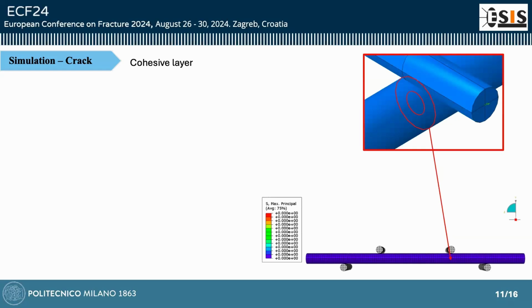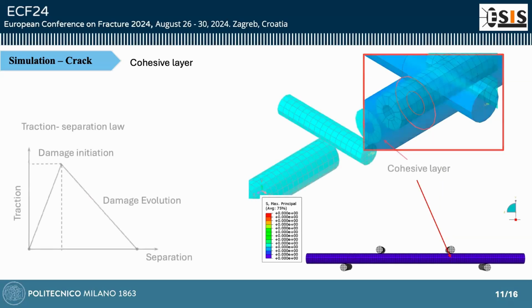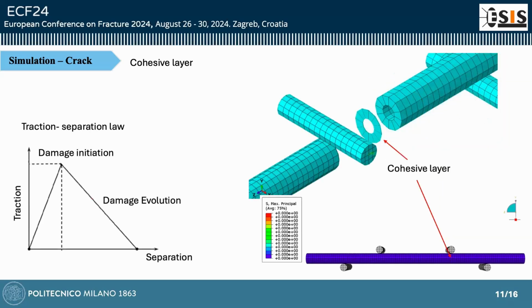According to the experiments, we know in advance where the crack is going to happen. So to simulate the composite filament, we are going to use a cohesive layer to model the crack. And the characterization of that cohesive layer is the traction separation law. As the tensile strength reaches its maximum value, it starts to progressively reduce, and after reaching the separation value, the element is going to be removed and the crack is going to form.